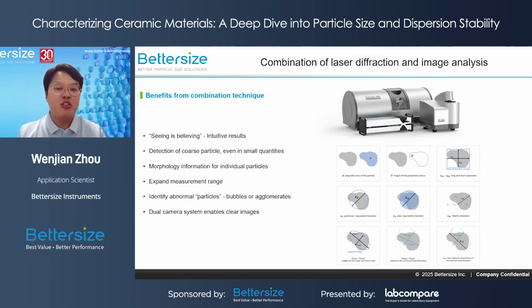Besides, the dynamic imaging system is highly sensitive to coarse particles, extending the upper measurement limit to 3,500 micrometers. The outlier particles, such as bubbles and agglomerates, can be reviewed because each particle is photographed, which can further be used to evaluate whether the dispersion status of the sample is good or not. Two cameras with different magnification are installed in the dynamic imaging system to ensure clear images of every particle. Therefore, measurement accuracy can be guaranteed.